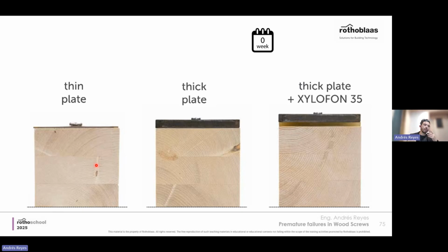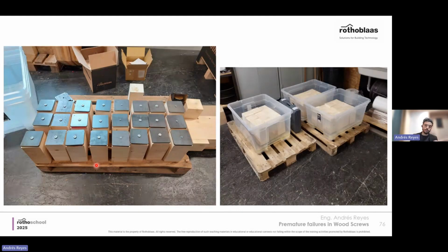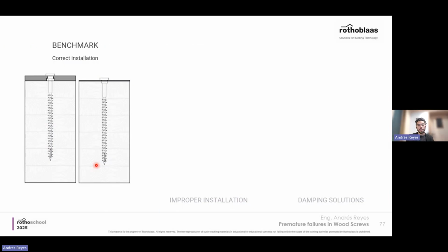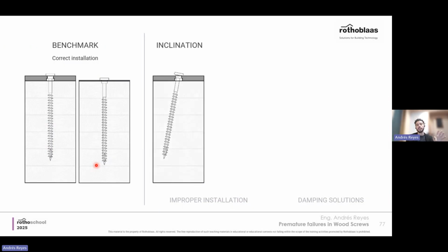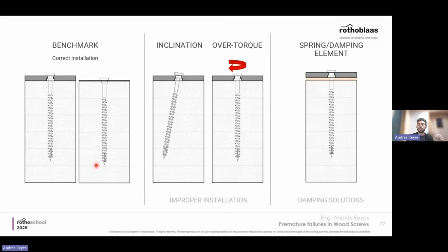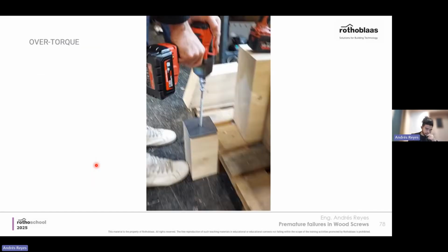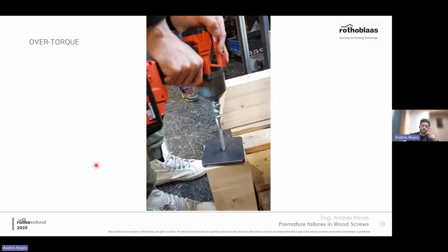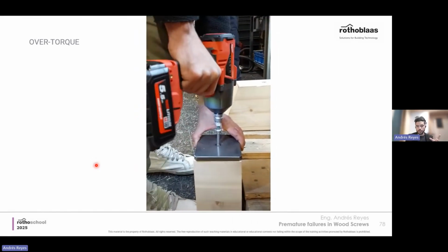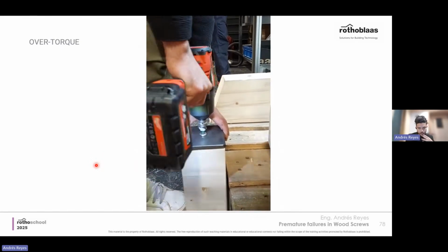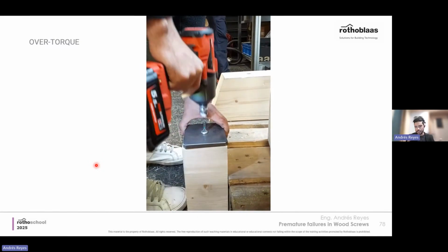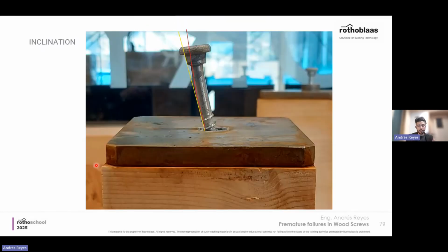We ask ourselves the question: can we break a screw via wood swelling, or via wood swelling and improper installation? So we put many samples into water, samples with the correct installation and samples with inclination, with over torque, and also adding some damping solutions like a soundproofing profile. In the cases of over torque, this is a case of over torquing with an impact wrench and stopping when the screw gets into contact. That way we will add a lot of added torsion.